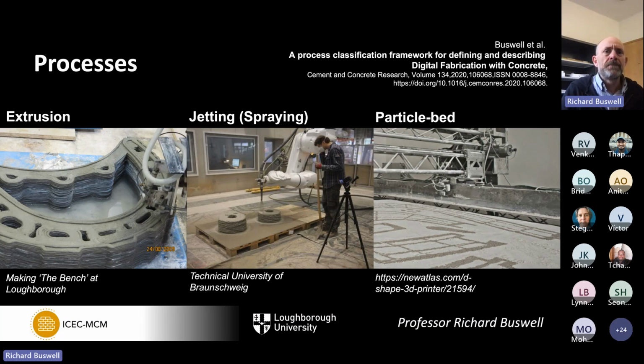So extrusion based. Jetting is really where we're spraying concrete, very much like shotcrete, although here you are spraying on top of wet concrete rather than on a hard surface. But the positioning is done much the same way as the extrusion. And out of interest, the material that the extrusion is based on is actually based on shotcrete type mix designs.